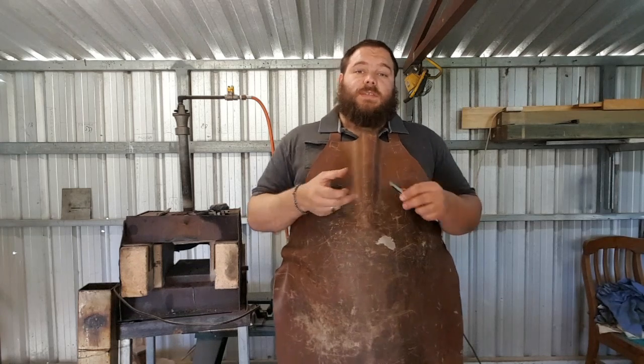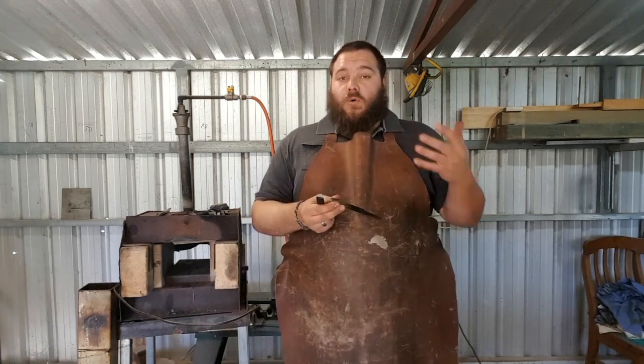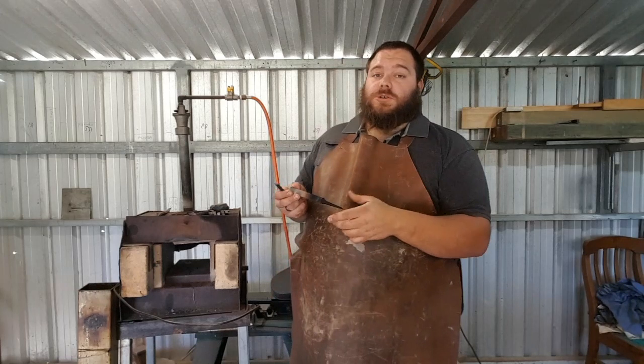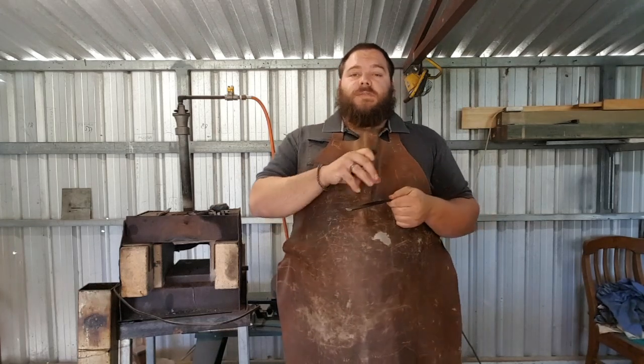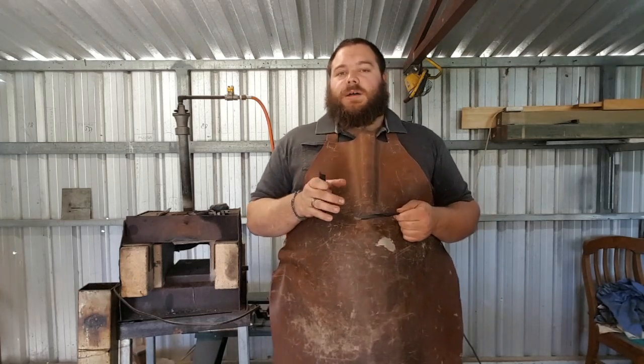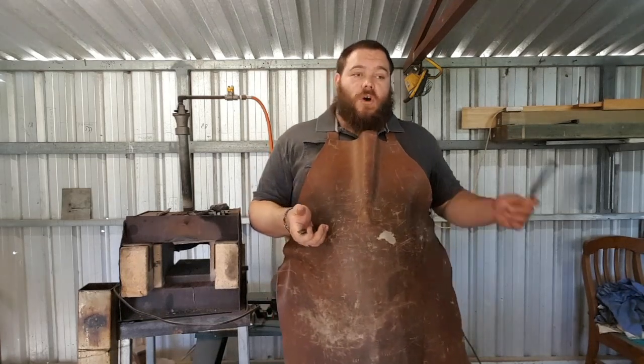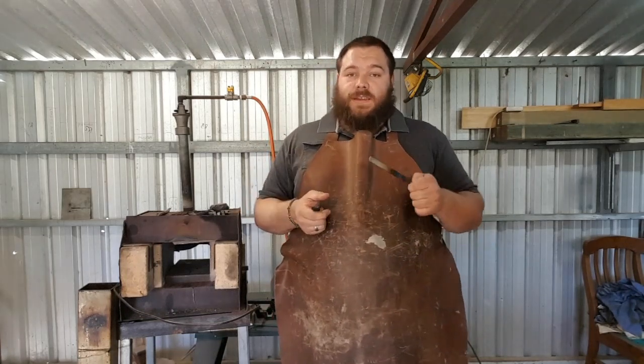And that was because they understood that it was only on the surface that the heat was coming from. And that's even more prevalent in torch tempers or forge tempers where you're waving it in front of the forge. The surface may get to that tempering temperature, but the center may not. And you can't just leave it to permeate, because sometimes you're going to overshoot that if you leave it for too long. So you've got to stop the temper and then go back and re-temper.